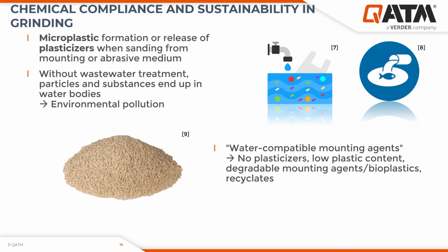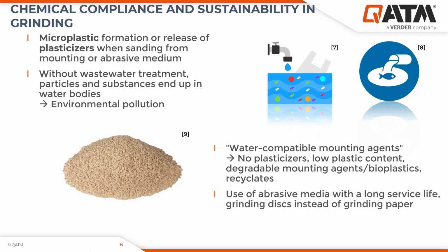Additionally, just a small informational reminder: not only the mounting resin is abraded down, but also the abrasive media over the course of its service life. So basically, if you have any system that is dependent on, for example, sandpaper, these sandpaper-based, grinding paper-based systems tend to release a lot of abrasive media as well into the grinding water. So exchanging it with a system that has a longer service life might be the proper way to comply with chemical regulations and overall to decrease the waste. So if you can, try to switch from grinding paper to, for example, grinding discs.